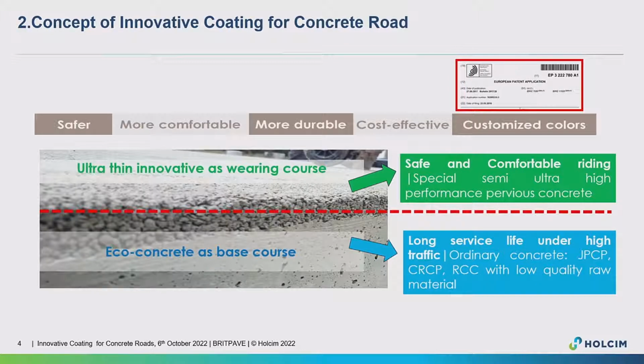So this is our concept, by separating the structure into two layers with separate functions. The first one is the semi-pervious concrete, which is very thin, up to only 3 centimeters, that can be placed wet on wet or wet on dry on an eco concrete. And the eco concrete we can name like the JPCP, CRCP, RCC, which use low quality raw materials that don't need to meet the quality criteria used for the top layer or the wearing layers.